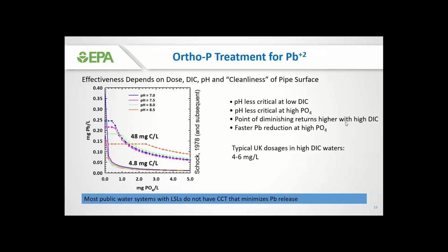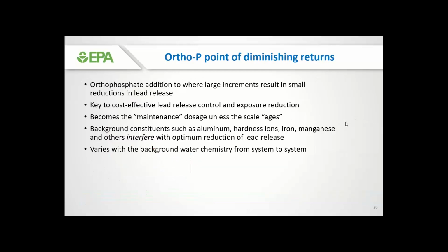But most public water systems with lead service lines do not have corrosion control that, strictly speaking, minimizes lead release, in the sense that we're absolutely at the lowest point of any of these curves, because it's really hard to achieve. So our colleague at EPA Region 5, Miguel Del Toral, coined this term of point of diminishing returns for orthophosphate, where basically he suggested adding orthophosphate up to a point after which additions of orthophosphate would result in small improvements, small reductions in lead release, and he suggested that that's the key to cost-effective lead release control.